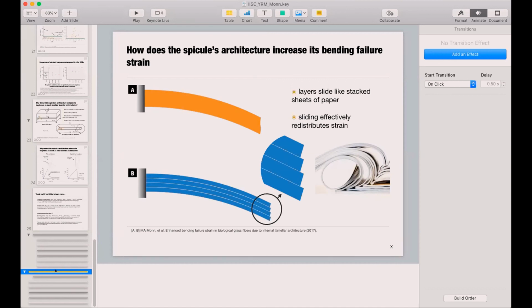And I agree. I think the outer layers of a spicule are likely sacrificial, that if they take most of the damage and most of the interior layers are defect-free or near defect-free, that can greatly increase the strength of the spicules. I also have done some other work looking at other internal deformation mechanisms that could allow greater flexibility in the spicules.